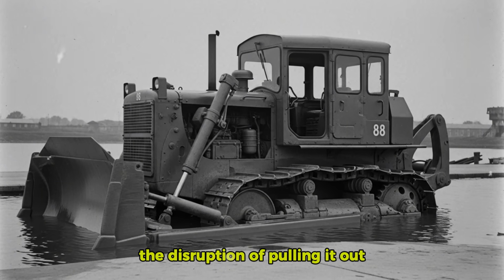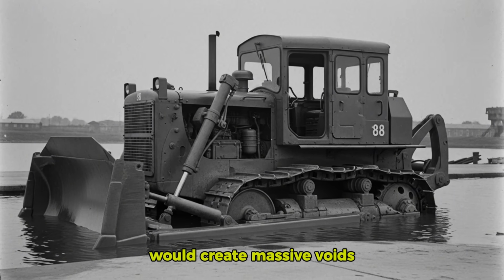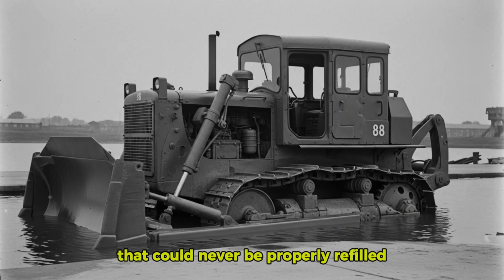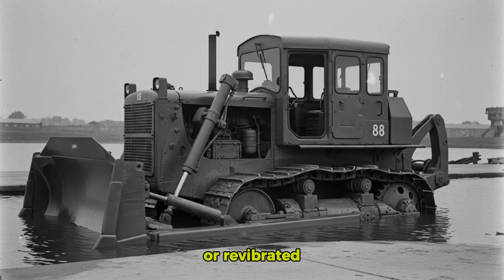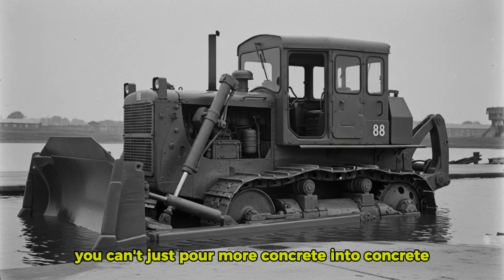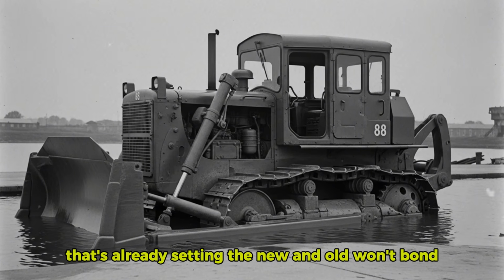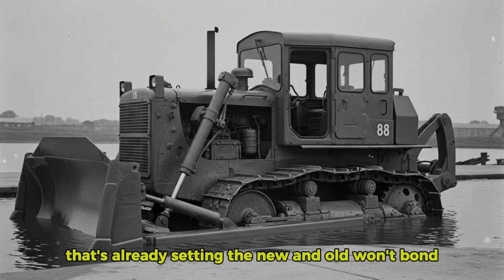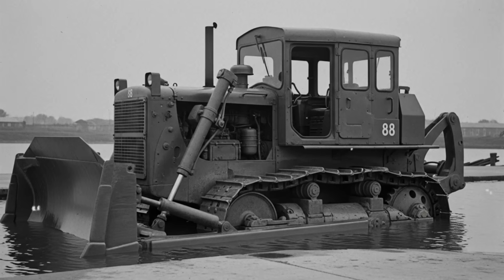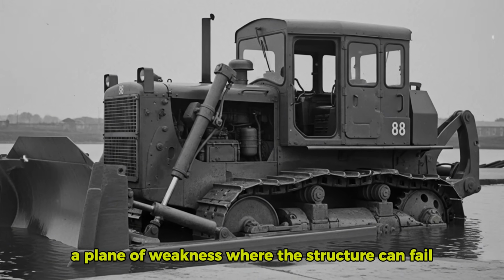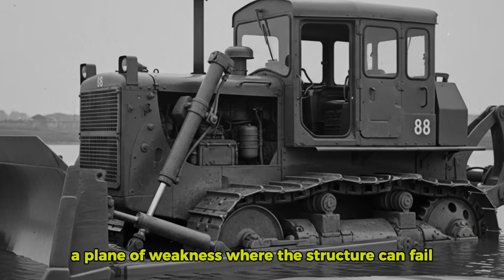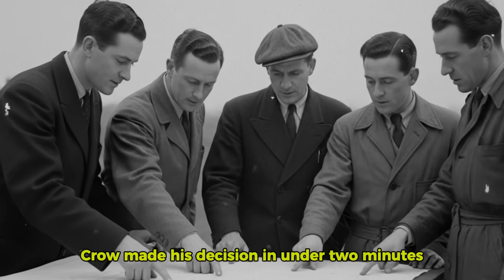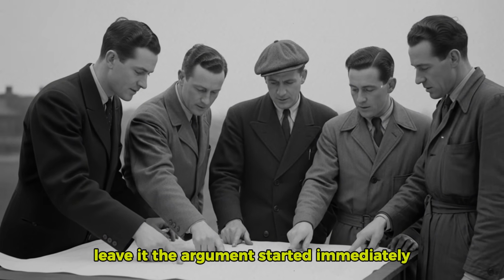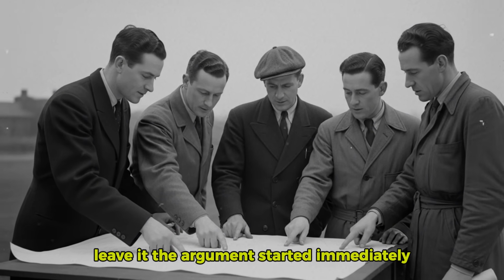Worse, the disruption of pulling it out would create massive voids and disturbed zones that could never be properly refilled or revibrated. You can't just pour more concrete into concrete that's already setting. The new and old won't bond. You get a cold joint, a plane of weakness where the structure can fail. Crowe made his decision in under 2 minutes. Leave it. The argument started immediately.